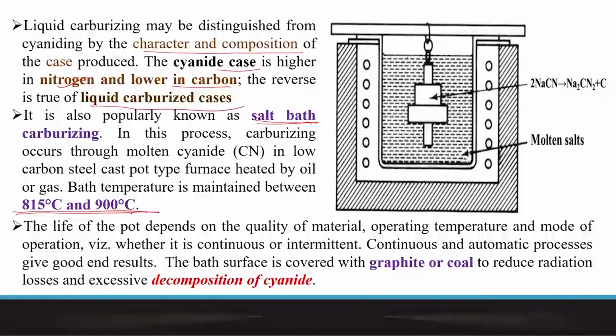Now, as I already mentioned, and no harm in repeating again, since we are not dealing with charcoal or coal or coke as the primary charge, but we are dealing with cyanide, excess decomposition of cyanide actually is to be prevented, and it should not lead to any kind of human or any other casualty. So this is the core reaction, and so this cyanide that we use goes to cyanamide and then releases carbon, and this carbon gets absorbed into the component.